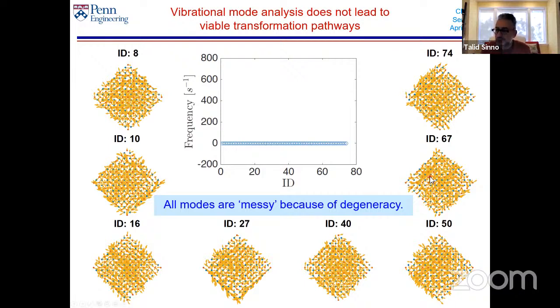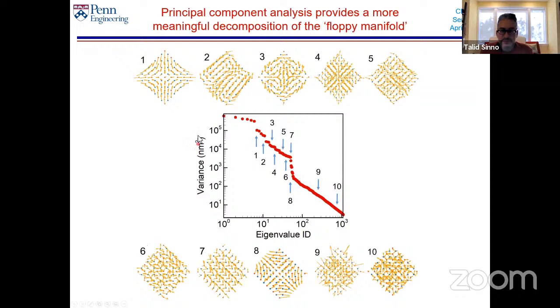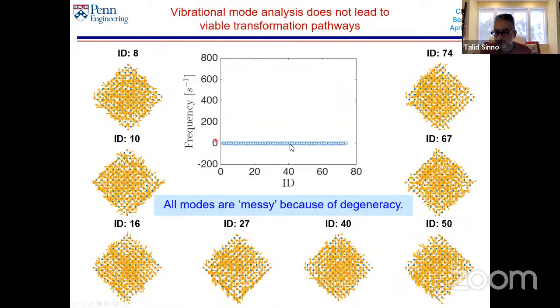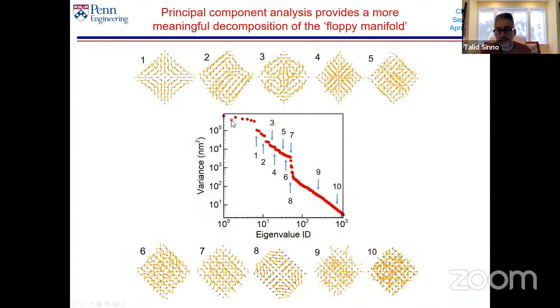There's no way to extract out clean dynamics because of this degeneracy. So what we did, this is when we started working with Celia and Paris, was a principal component analysis, and we tried to find an automatic way of ordering these modes. Instead of separating them based on frequency, we tried to separate them based on variance. And now when you separate them based on their extent or their variance, it's no longer degenerate.